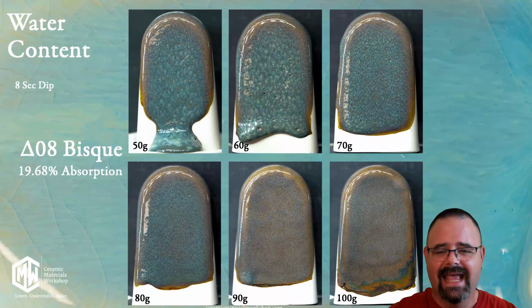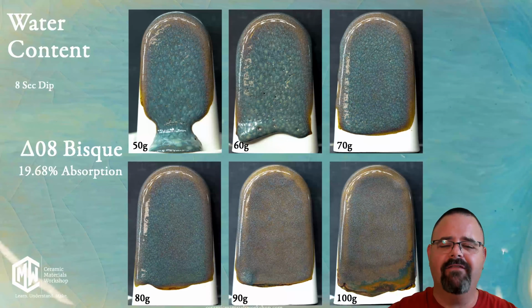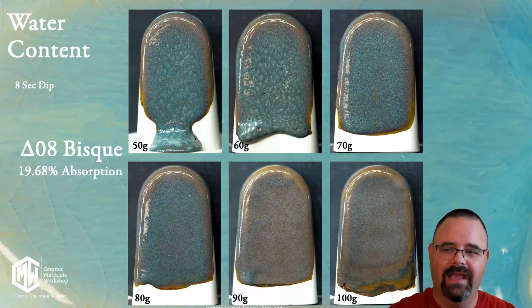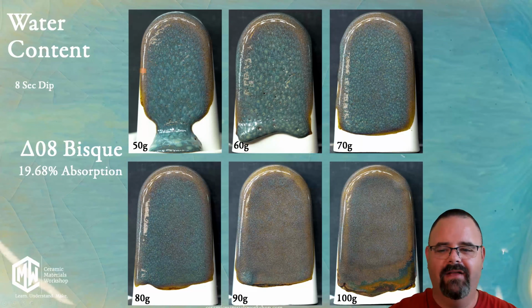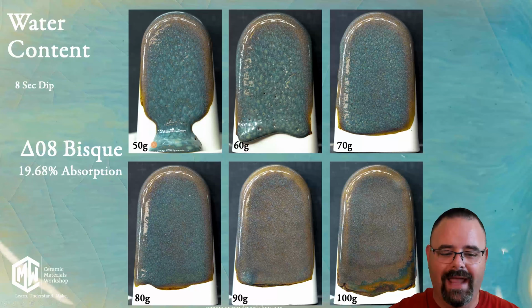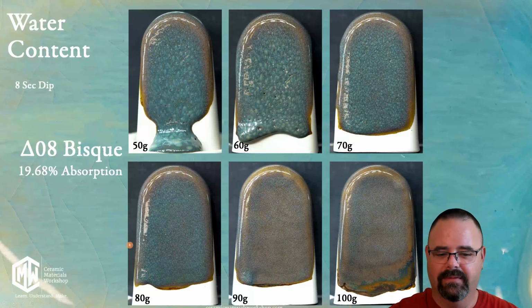You see, this is all the same glaze, but now I've mixed it with different water contents, but used the same application time. So these are all with the 8-second dip with a cone 08 bisque. But this tile is mixed with 50 grams of water. This is 60, 70, 80, 90, and 100. And amazingly enough, now the 100 grams of water at 8 seconds at a cone 08 bisque looks like our previous sample at 50 grams of water with a 2-second dip, right?